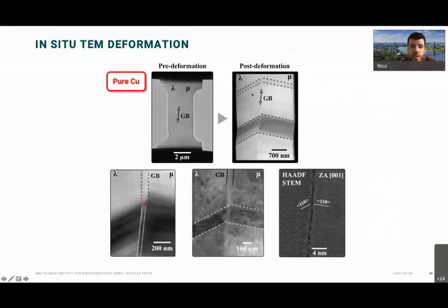And here is what happens. If we have the pure copper grain boundary and we do a dog bone shape and deform it under tension, we form these deformation features. And typically we form 1 or 2 small ones, and then one grows in size very long. We also observe that the width of the grain boundary decreases. We have very defined orientations, which actually coincide with the 110 orientations from the crystallography, which is nice. Because that means, okay, this is more or less related to slip in copper, right?